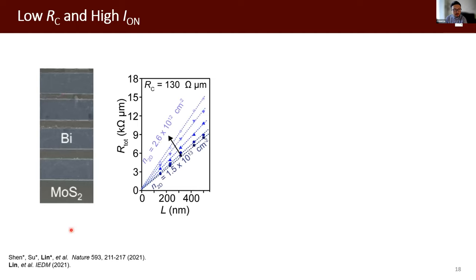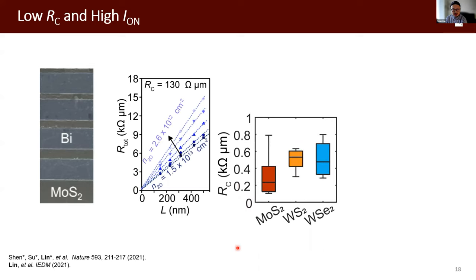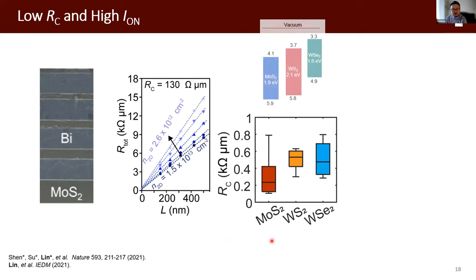Then we fabricated a series of devices with different channel length. And when we measure the total resistance versus the channel length, we can use the y-intercept to extract the contact resistance. The value is indeed very low. Using a similar approach, we can extract the contact resistance when bismuth is in contact with a variety of different 2D semiconductors like MoS2, WS2, WSe2. They are all well below 1 kilo ohm micrometer. So I will show later, these are the best reported value for all three materials so far.